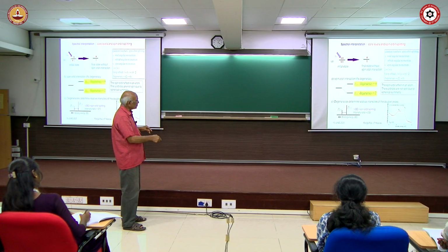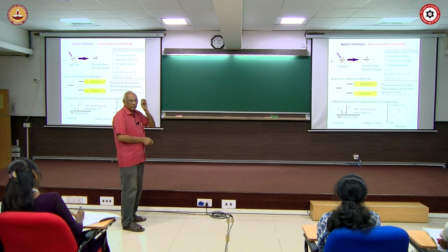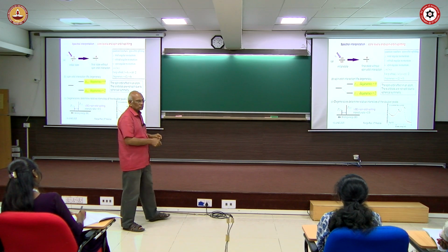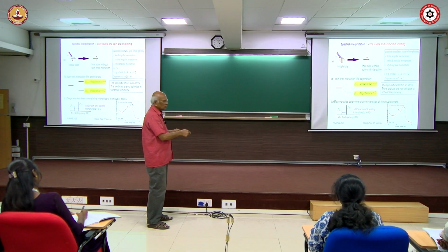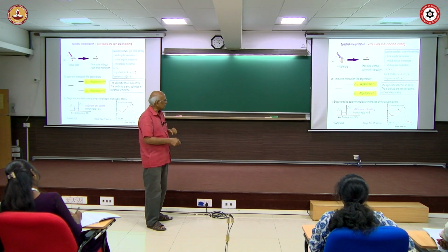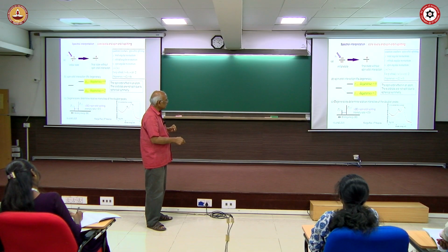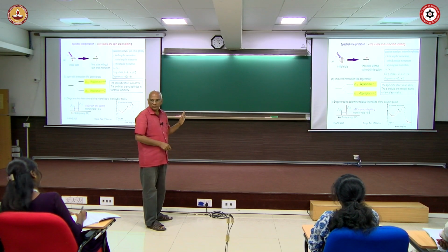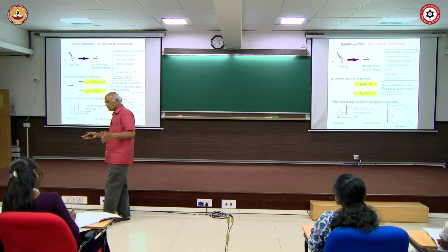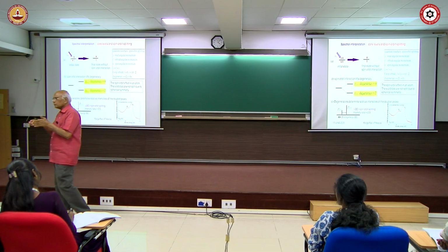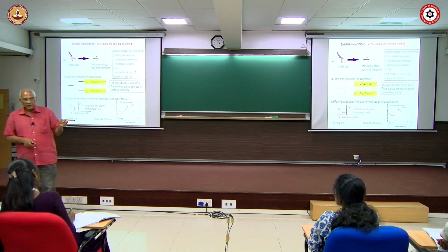So the intensity ratio is 0.5, 1 by 2 divided by 3 by 2 is equal to 0.5, or if you take it the other way around, it is going to be 2, either 4 by 2 or 2 by 4 is basically what you are looking at, okay. So that is the energy difference and that is the intensity difference. Now you know why intensities are different and why you are getting two peaks for the p orbital.